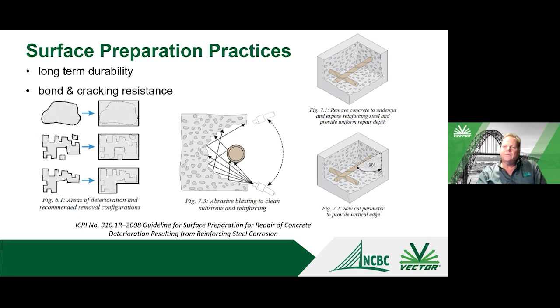So having saw cut edges around the edge gives you a nice good shoulder for the repair material to bond to. And then once again, cleaning, you need to clean the steel very well. You want to get rid of all the corrosion product off the reinforcing steel. Make sure you remove any residual cement and chlorides from the steel, and pay particular attention to the back of the bars. Make sure that you clean those as well.